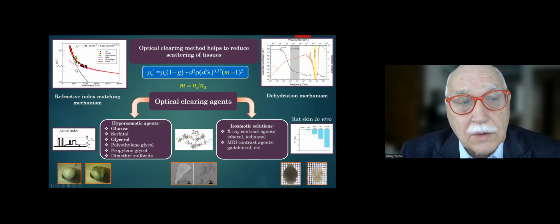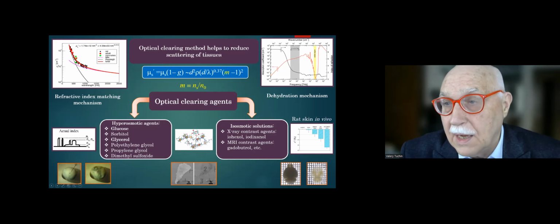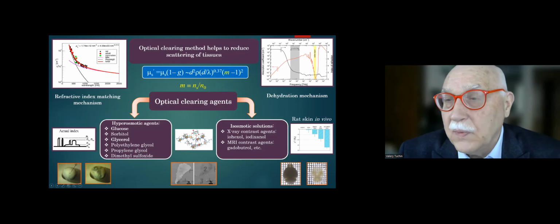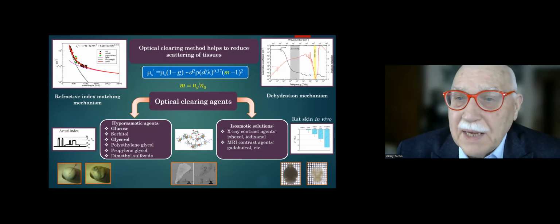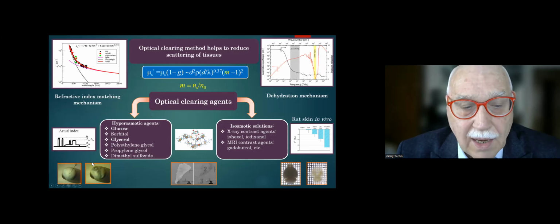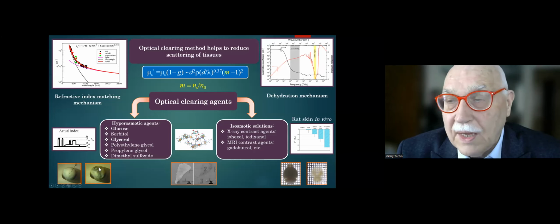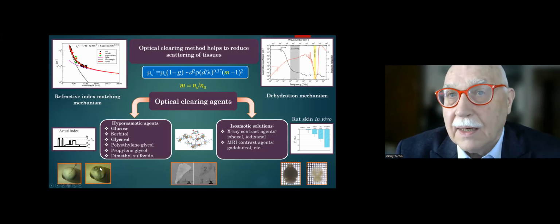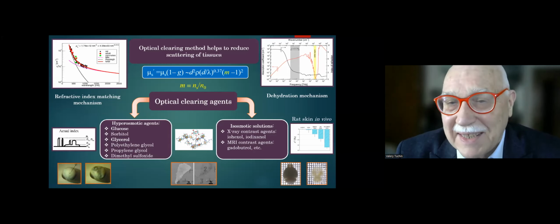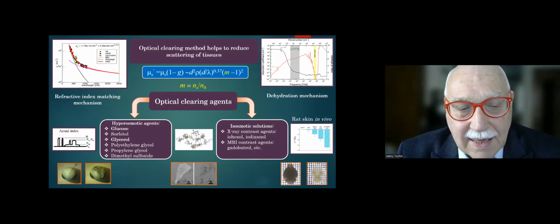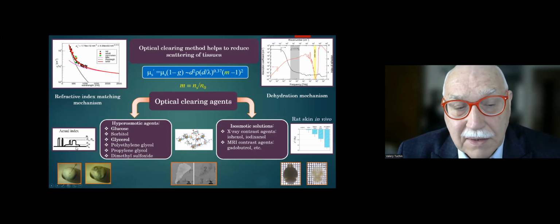I would like to talk about the ultraviolet part of the spectrum and also about the terahertz. And you see here that the scattering is huge here, and for the terahertz range, absorption is huge. So if we find some agent or some liquid which can be impregnated into the tissue, like here, you see here some drop of the clearing agent. So it dehydrates tissue and equalizes the refractive index to match the refractive index of the scatterers.